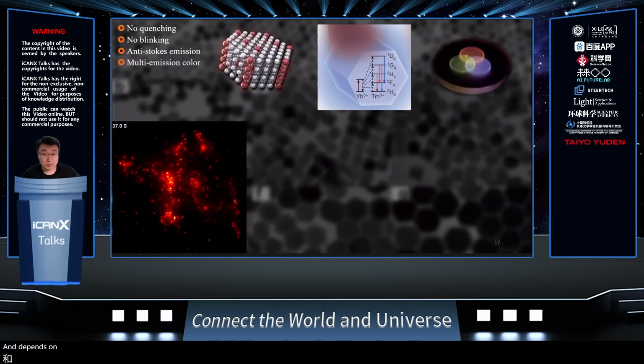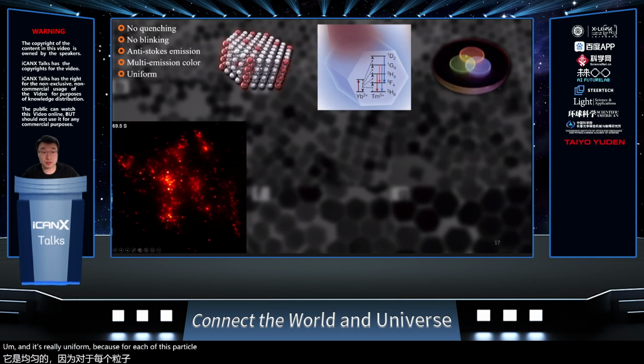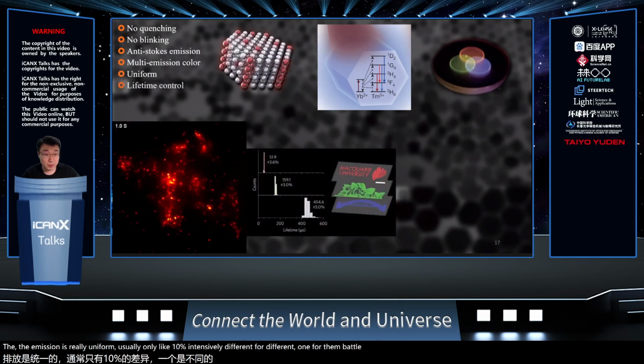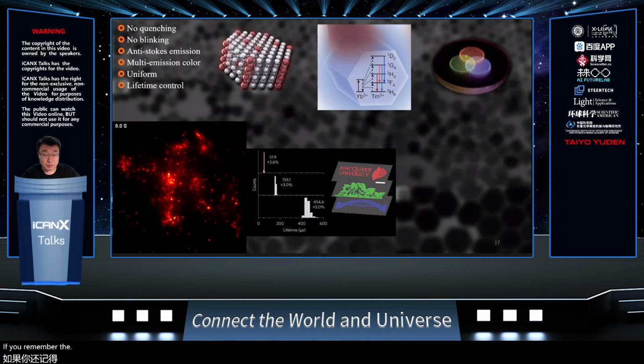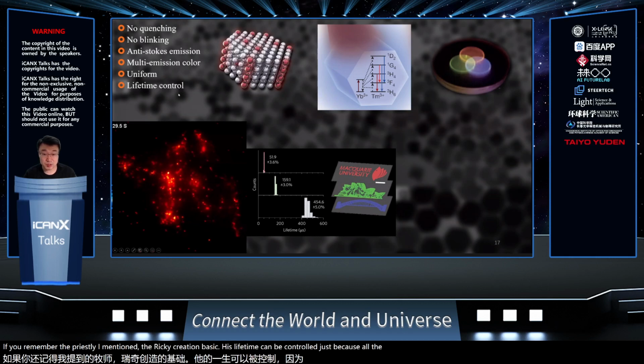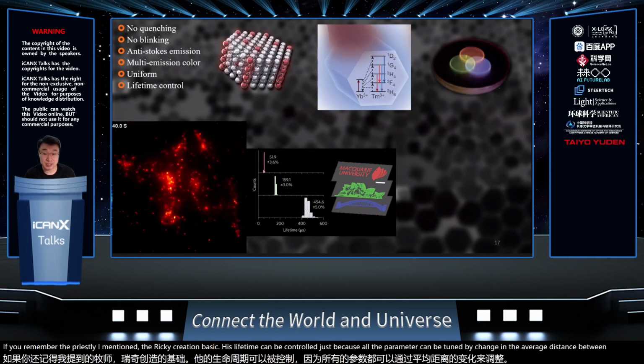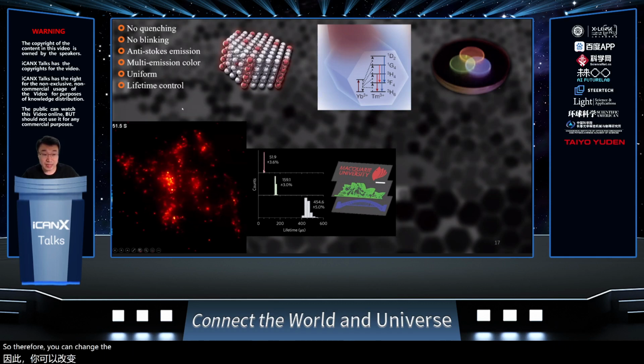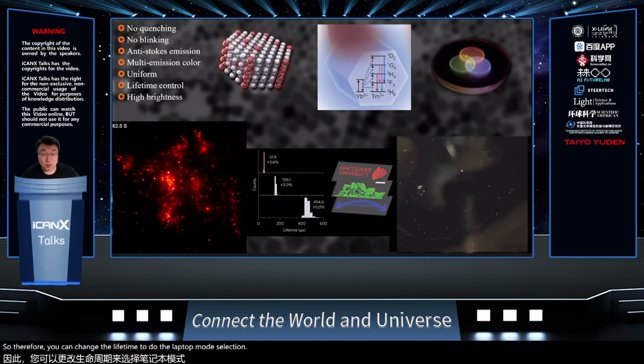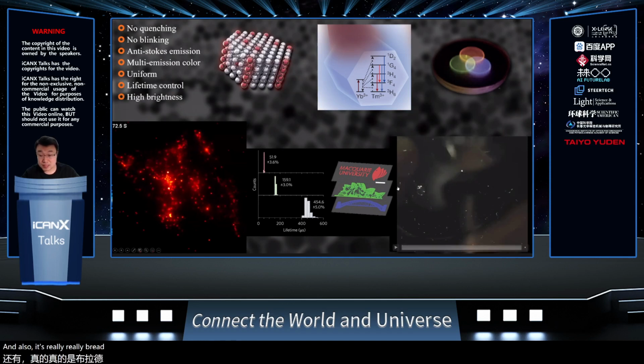Depending on the doping element, you can also change the emission color. And it's really uniform, because each particle contains thousands of emitters. Therefore, the emission is really uniform, usually only about 10% intensity difference between particles in one batch. If you remember the rate equations I mentioned previously, the lifetime can be controlled, because all the parameters can be tuned by changing the average distance between the different ions. So you can change the lifetime to do lifetime multiplexing. And also, it's really, really bright, comparable with quantum dots.